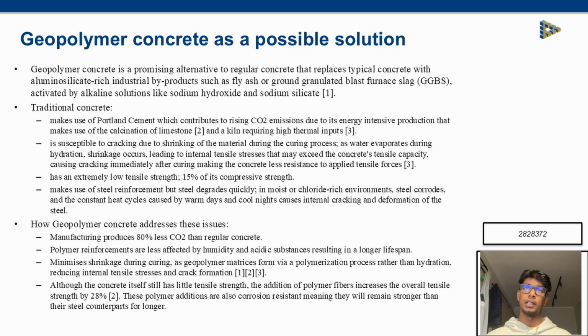Geopolymer concrete addresses these issues. The manufacturing process produces 80% less carbon dioxide. Polymer reinforcements are less affected by humidity and acidity. The minimal shrinkage during curing allows for a stronger, more versatile structure. And the concrete itself has little tensile strength, but the addition of simple carbon polymer can increase the tensile strength by up to 28%.